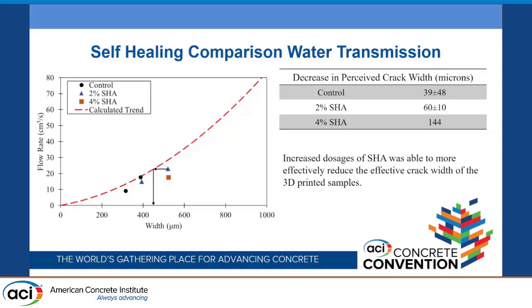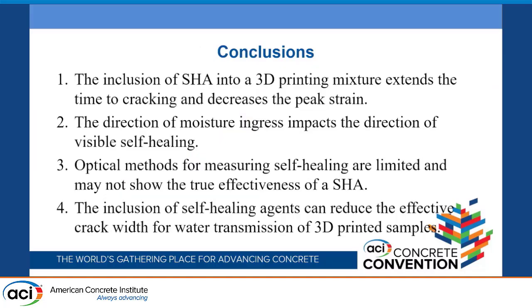From these results, we can take a couple of conclusions. First and foremost, the inclusion of a self-healing agent in a 3D printing mixture will extend the time to cracking and decrease the peak strain. That the direction of moisture ingress will impact the direction of visible self-healing, impacting how you're actually perceiving your self-healing agent effectiveness. That optical methods for measuring self-healing are going to be limited and not always show the true effectiveness of the self-healing agents, and that the inclusion of self-healing agent can reduce the effective crack widths for water transmission of 3D printed samples.